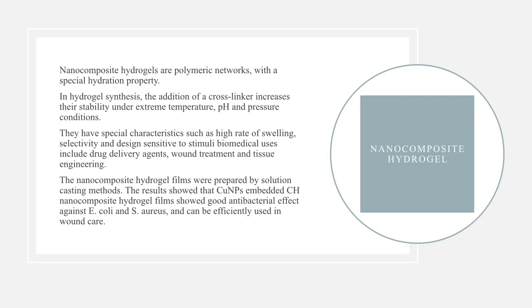The nanocomposite hydrogel films were prepared by solution casting methods. The results showed that the copper nanoparticles embedded chitosan nanocomposite hydrogel films showed a good antibacterial effect against E. coli and S. aureus and can be efficiently used in wound care.